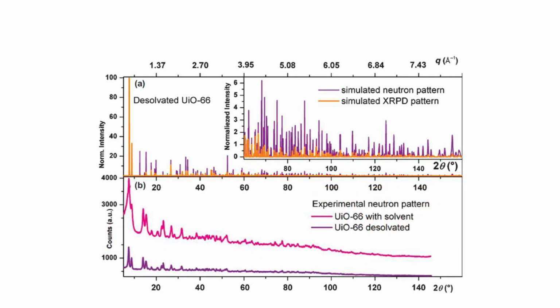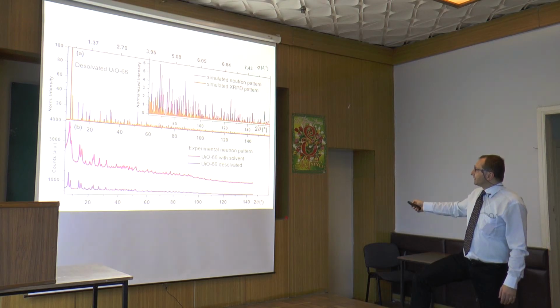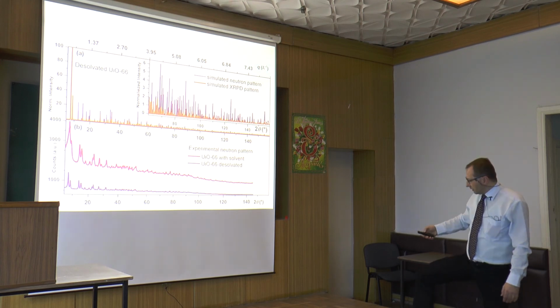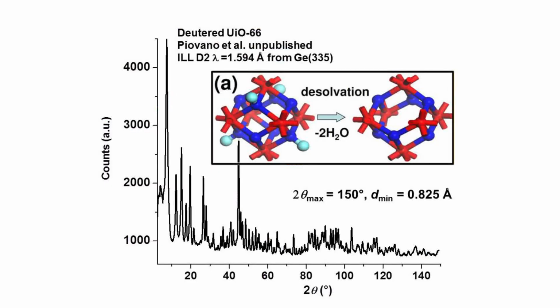Okay, then in order to locate this hydrogen atom that we have seen by infrared, and which is fundamental in our model, we need to run neutron powder diffraction, and see how important it is that powder diffraction is able to give high signal, even at high Q, the exchanged vector. These are the data that we collected just recently at ILL that are under analysis.